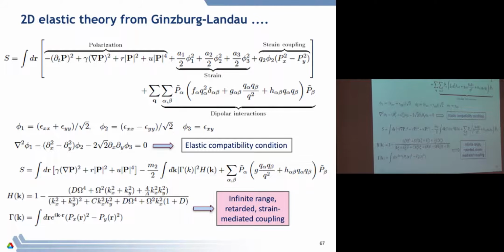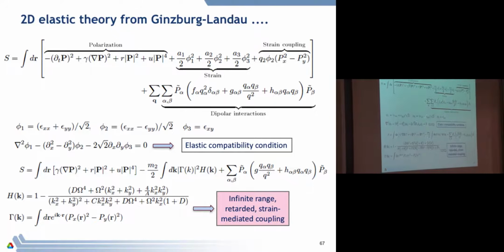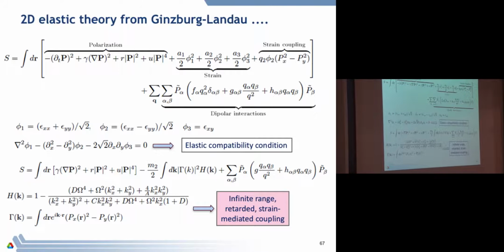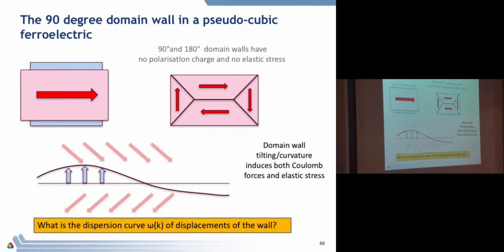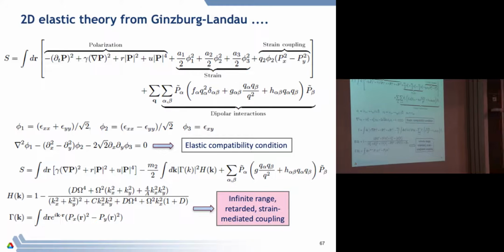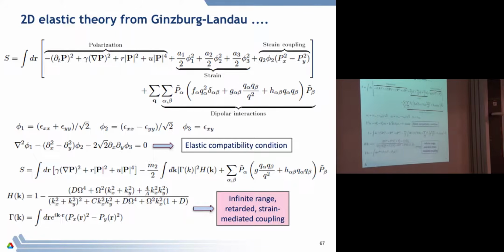Okay. They're coupled, and in this case they're coupled with this term, which is square to rectangle, coupling to the difference in the polarization. Okay. The term exists by symmetry. That's why when the polarization happens, this thing changes shape. Okay. So that's that term. And then there's dipolar Coulomb terms that I won't play much about.